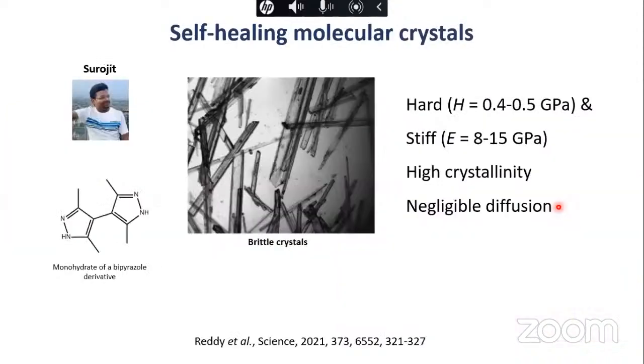So we were looking at these crystals from the mechanical property point of view. And my student Surojit, who has just joined as a postdoc in a different group in the US, was looking at these crystals. He made this ligand for some other purpose, but since he got very good crystals, he looked at them. He found that these crystals are very brittle, very hard and also stiff, the elastic modulus is around 8 to 15 GPa, and these are highly crystalline. And since these are highly crystalline, diffusion is almost not possible in these crystals.